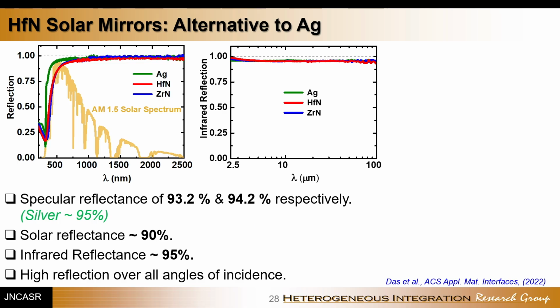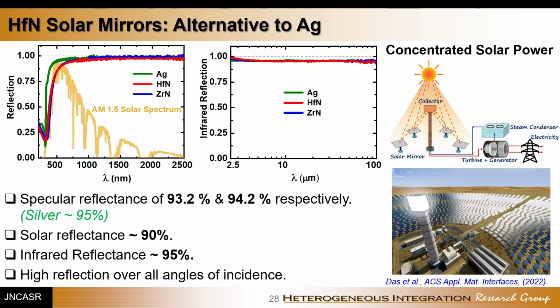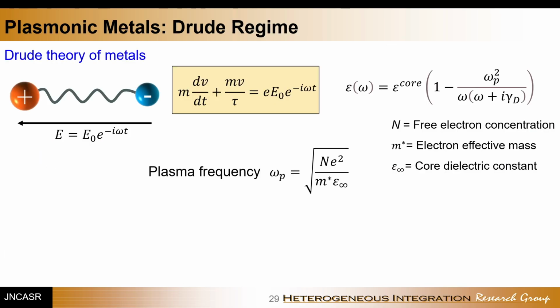And hafnium nitride and zirconium nitride have around 93 to 94% reflectivity. Then the solar reflectance and infrared reflectance are also very high in both materials. So the question that we really wanted to answer at that particular point is, if you really want to use it for practical application, how thick a hafnium nitride or zirconium nitride do you need? And that really led us to find a new physics in this domain.